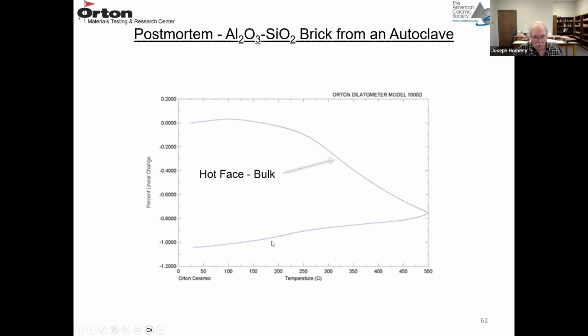And then cooling down tends to be linear again. Probably should have been run to a little bit higher temperature. This would have been more linear on the cool down after we remove the volatile compounds. So this is just showing you where these volatile compounds are coming off in this temperature range between 100 and 500 degrees C. So thermal expansion is useful in various ways in a failure analysis.